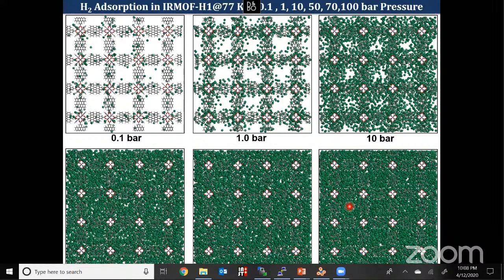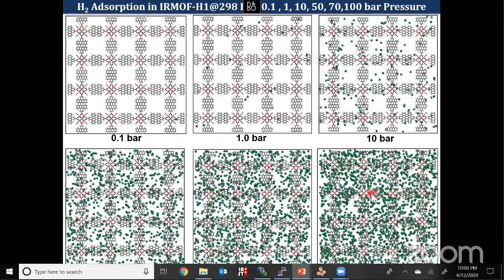All these simulations were run at 77 Kelvin, and this one at 298 Kelvin. Here you can see that at room temperature, the material is not adsorbing many hydrogen molecules. That means it doesn't have any open metal site or effective binding site. So this material can't store hydrogen near room temperature, which means we can use this material for hydrogen purification. If other gases are attracted and bound by this linker or weakly bind with this metal cluster, then in that scenario this material can be used for hydrogen separation. The hydrogen molecule won't bind that effectively with this material, so we can use it for separation.